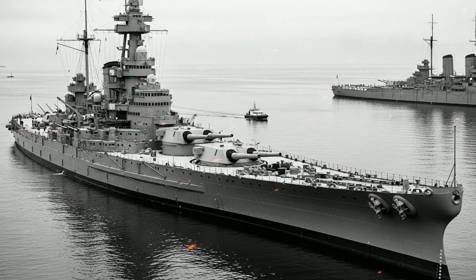German Krupp cemented armor used in Bismarck and Tirpitz showed similar advantages. The American disadvantage stemmed from testing procedures, not inferior metallurgical science. American armor testing prioritized ensuring that shells would not penetrate intact and able to detonate. As American armor-piercing shells grew stronger through the 1920s and 30s, test standards required thicker, harder face layers to shatter those shells. The extremely hard face helped against weaker shells, but created brittleness problems against the most powerful projectiles, which could penetrate the brittle face in damaged condition rather than being kept out entirely.